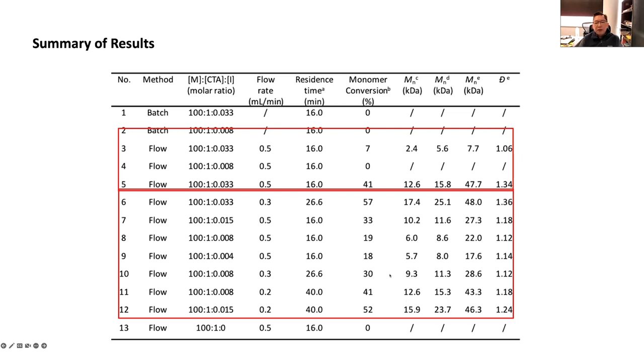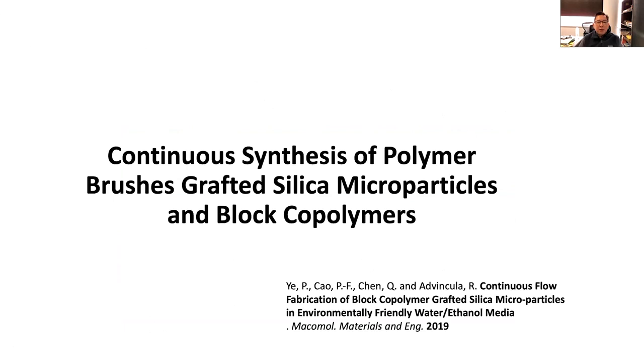Conversion is more or less anywhere between 18 to 60%. Also, on the other hand, by controlling the ratio, we can get different types of molecular weight. And then finally, by controlling both the temperature and pressure, we can use the conversion for reaction time as well. And this was published back in 2019.